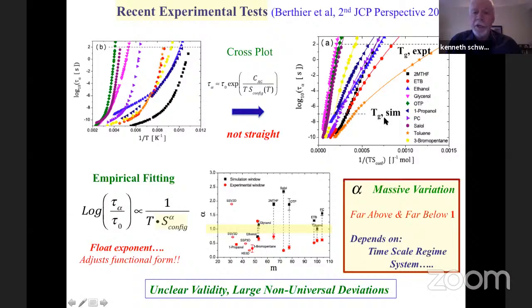This would be where the TG in simulation is and where TG in experiment is. And it's occasionally straight on one of these. It seems to be never straight on all of them, but overall there's a lot of curvature. So it's not straight, at least it's not straight to my eye. And this led to the idea, and there's some theoretical arguments about this, that, well, maybe it's not 1/configurational entropy. Maybe you have to raise it to an exponent. So you can do the empirical exercise of varying the exponent on a system by system basis to try to straighten this.